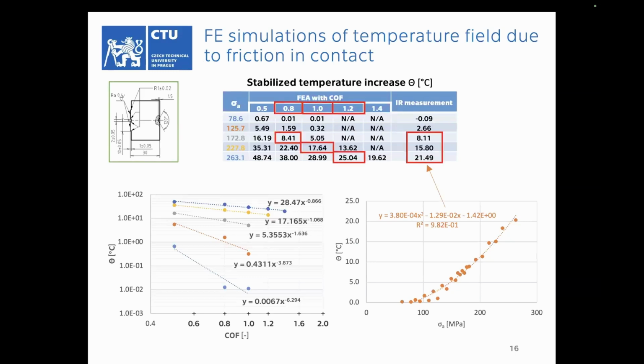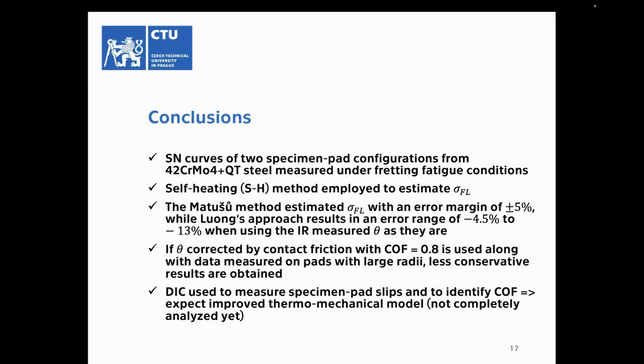For the bridge pads, we were facing even more problems. If you take a look at this data for high stress amplitudes, we get, even for very high coefficients of friction, temperatures still above the measured ones. So only very high coefficients of friction lead to data that can be used to subtract from the measured temperatures. So in this case, we decided that this numerical procedure doesn't make much sense. Yeah, this is not a very happy ending.